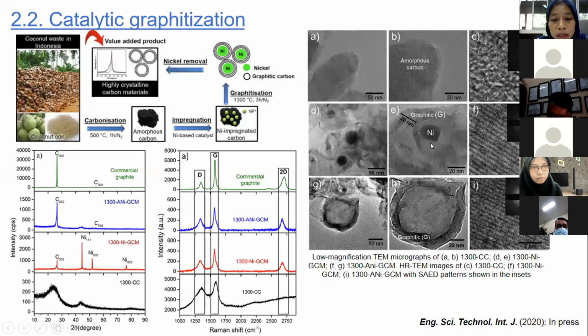In the low magnification TEM image of the nickel treated sample, we see spherical projections with nickel nanoparticles in their core. And the high resolution TEM image shows shells around the nickel nanoparticles with well-defined lattice fringes, and the graphitic layers were separated by an interplanar distance of about 0.3367 nanometer. It's closer to the lattice spacing of commercial graphite powder.